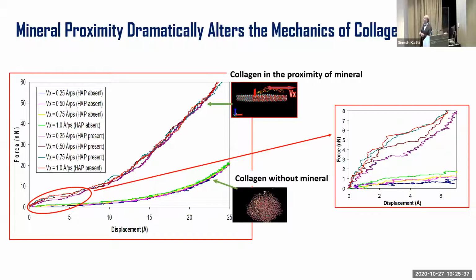And basically what we found is that when collagen is in the proximity of the mineral, a much higher load or force is needed to pull that collagen compared to the situation without the mineral, just like in nacre. So again, we see similarities between nacre and the bone here. In fact, this is telling us that the mineral is influencing the collagen in its proximity. Now, up to this point, the collagen and the mineral were always treated separately.